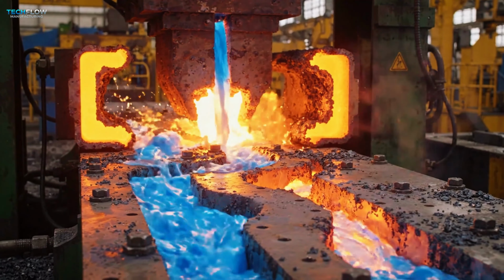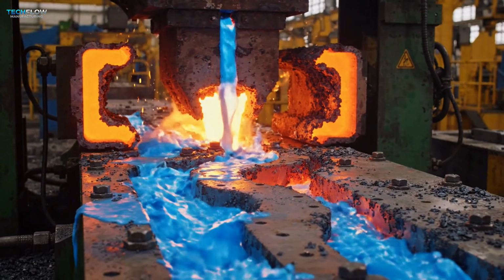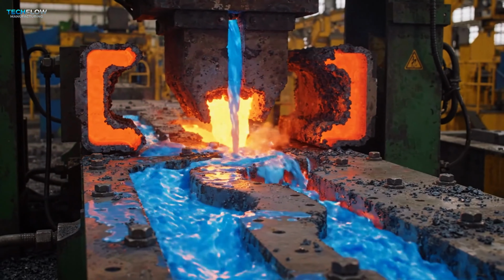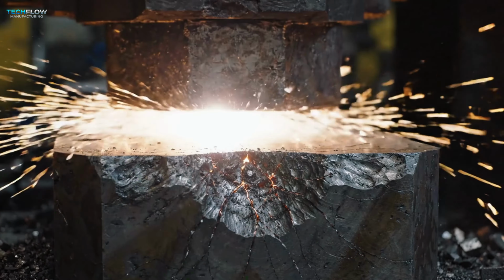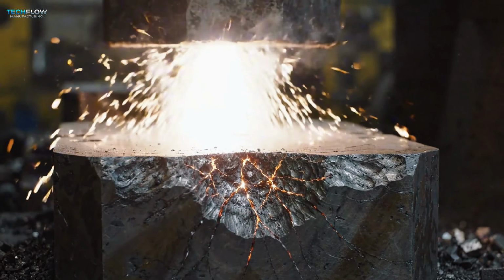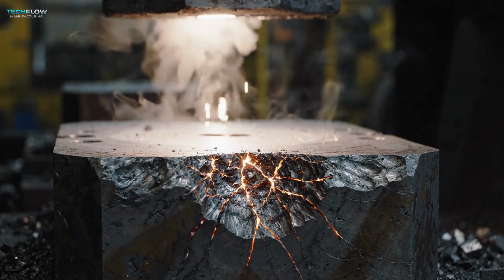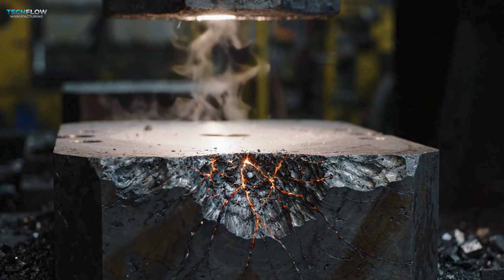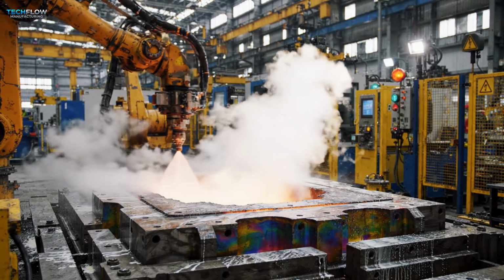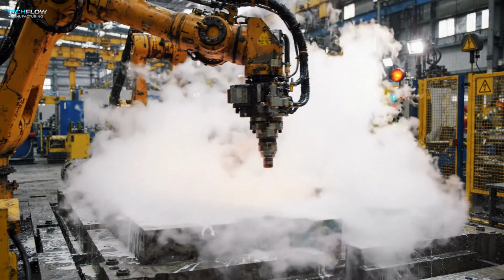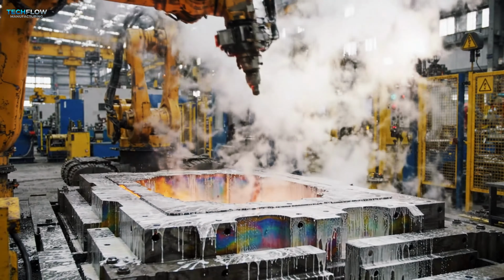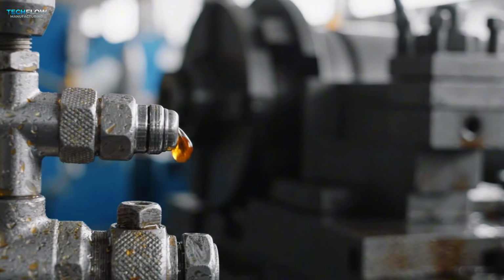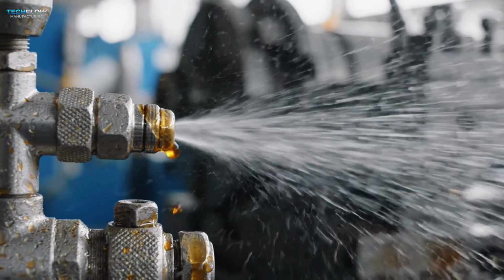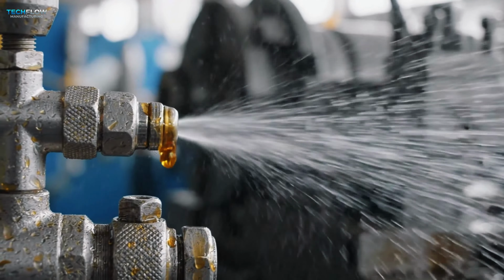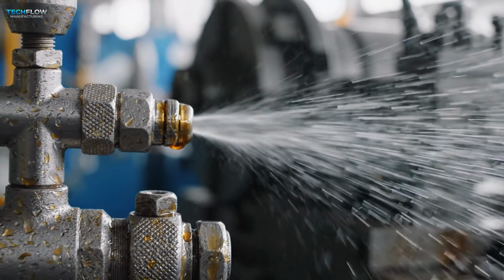Internal cooling channels within the die, controlled by laser-drilled passages, extract heat at an extraordinary rate. The thermal shock on the steel mold is immense. It must expand and contract predictably thousands of times without cracking. Specialized lubricants are sprayed onto the die faces between every cycle to prevent the aluminum from soldering to the steel. Every drop of lubricant is measured by automated nozzles, ensuring a microscopic, uniform film across the entire surface.